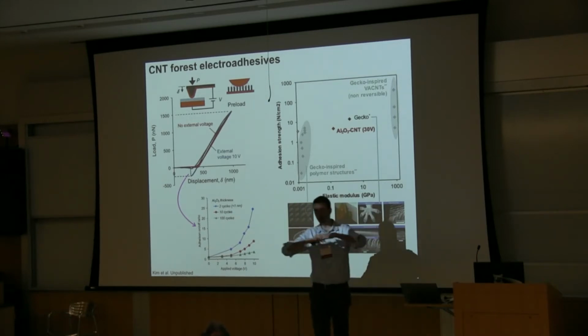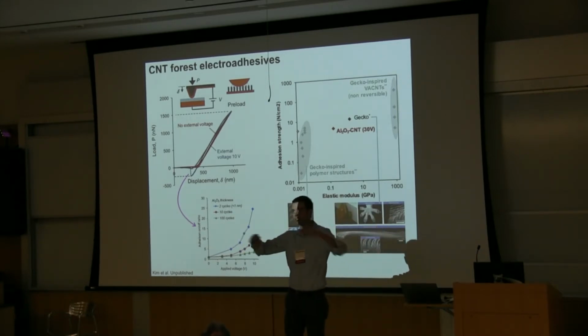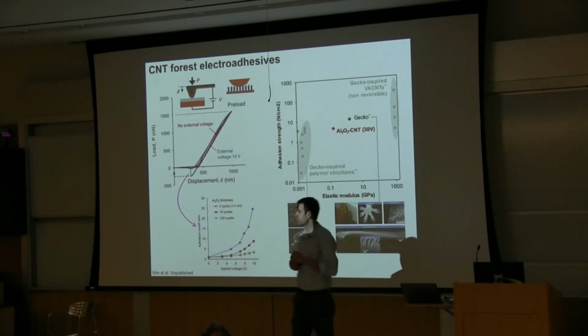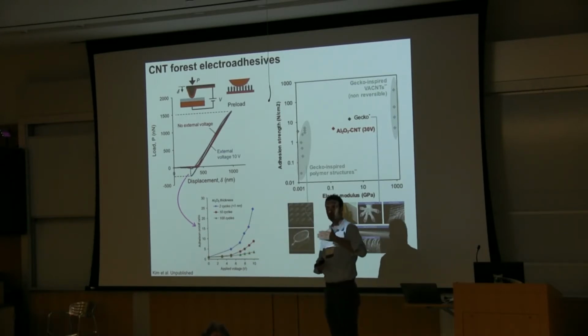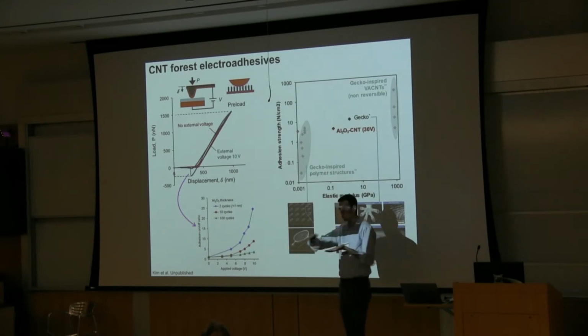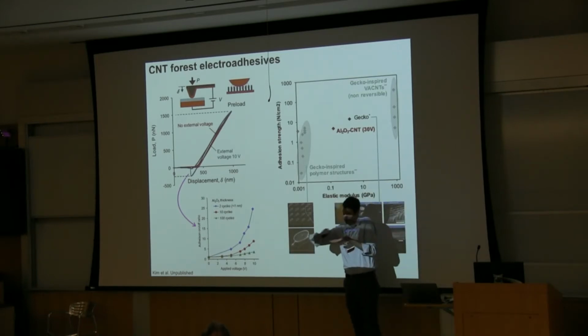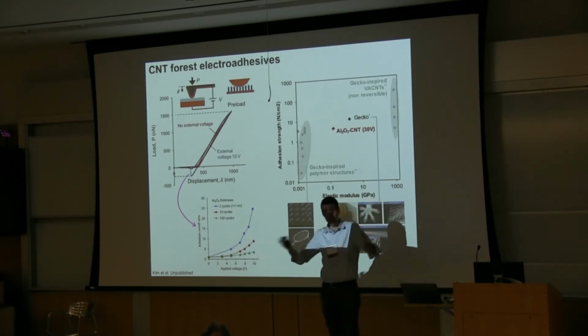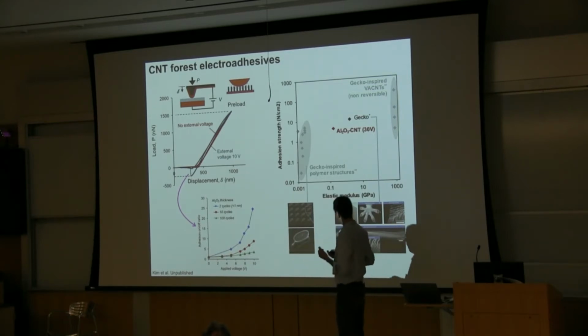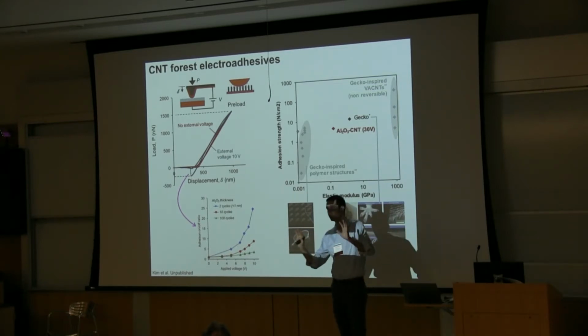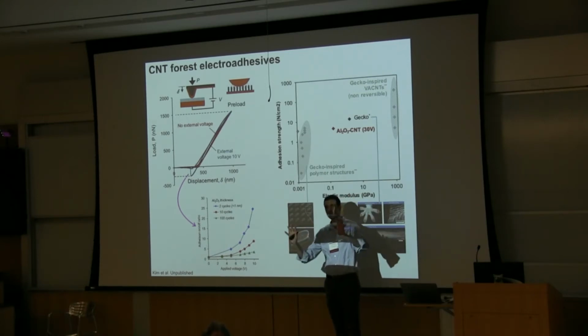The idea is that the alumina coating kind of blocks the intrinsic van der Waals adhesion between the surfaces, but if you apply voltage across it, you can get adhesion back. And we're interested in using these small nanotubes as stamps for placing very small devices. If I extrapolate to the macro scale, it's kind of like a gecko adhesive, but a gecko adhesive that's switchable.